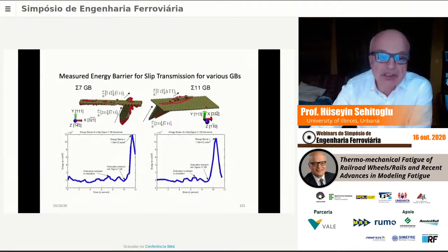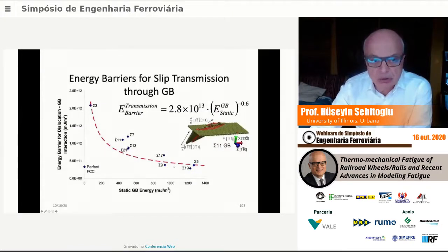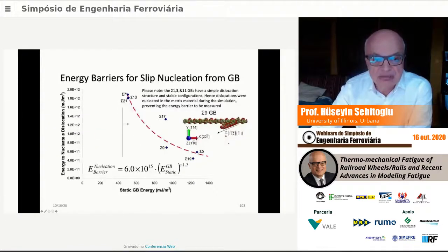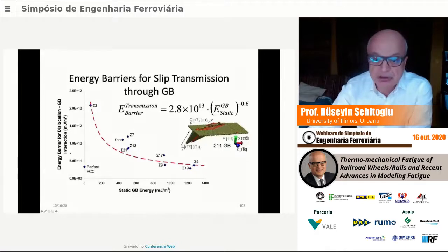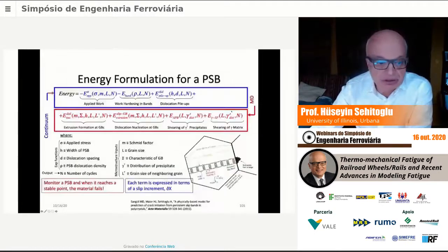And we established that for sigma 7, 11. This is a number that is called coincident site lattice. Number 7 means every 7th atom is in coincident site lattice at that grain boundary between the top and the bottom grain. And we established the transmission barriers. We established the nucleation barriers. This is the static grain boundary energy. This is the energy to nucleate dislocation. Previously, this is the energy to transmit through the boundary.